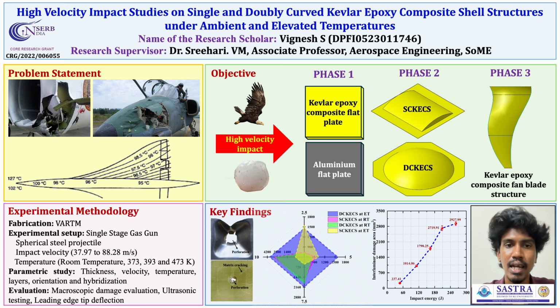In phase 3, the gas turbine fan blade impact was done and reveals that at lower impact energy, the energy dissipates globally, resulting in less interlaminar damage area and higher leading edge tip deflection. While at higher impact energy, the energy dissipates more locally at the contact zone than globally, resulting in lower leading edge tip deflection.